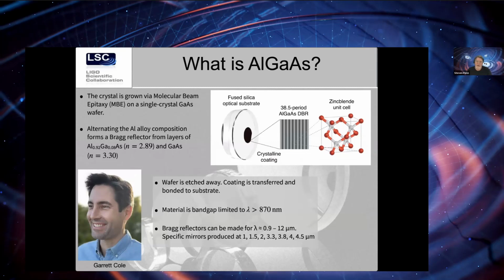So what is AlGaAs? It's different than the coating technologies that we've used thus far in all gravitational wave detectors. It's a crystal. It's grown via molecular beam epitaxy on a single GaAs wafer. It's a multi-layer, single crystal, where you change the doping level of aluminum, replacing the gallium, in order to change the index. The specific AlGaAs layer has a lower index, and the GaAs layer has a higher index, and you pair those together to make a Bragg reflector. Then the wafer is etched away and the coating is transferred over to the substrate.